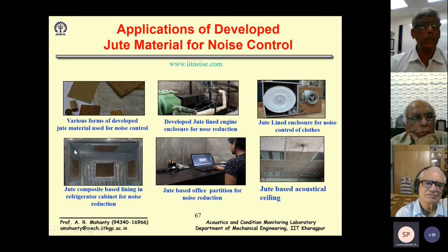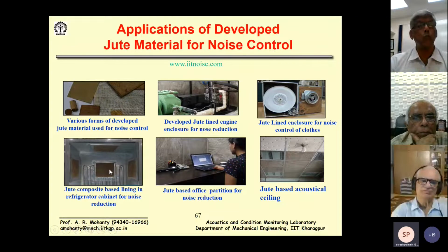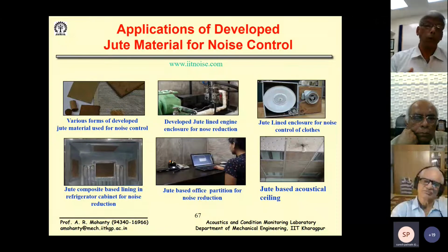And actually, this is the sheet metal steel onto which... when you open a refrigerator door, you see a white plastic casing or a polythene casing. Between that white polythene and the sheet metal, they put in foam, which is used as a thermal insulator. But these foams are not good acoustic insulators. So what we did is we put these barriers, and they could reduce the evaporator noise by about 5 decibels.